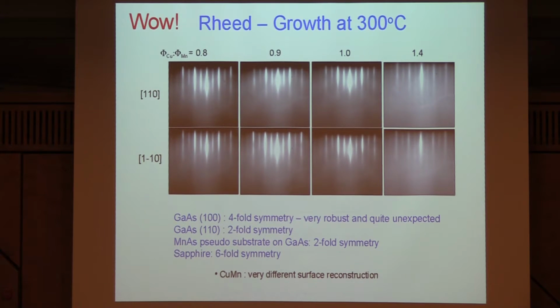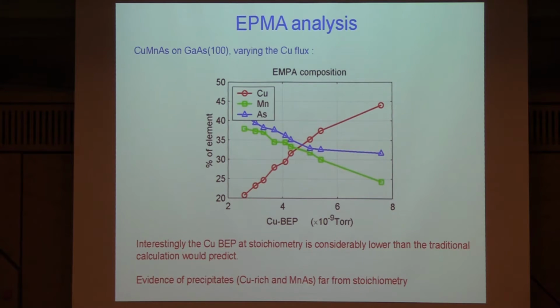Okay, and so we tried various different things. Nothing really told us exactly what we had, but there were hints. We looked at the wafers you've just seen, and several more in the same set. We varied the copper in this particular case, so we're basically going from excess copper to a deficit of copper. And we got this result. So this crossing point is clearly stoichiometry.